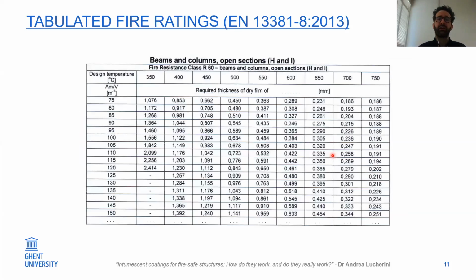So as I mentioned, there are some different engineering methods, implicit engineering methods, to design intumescent coatings, and the first one is the tabulated fire ratings according to the standard EN 13381 part 8. You can see, for example, that intumescent coating manufacturers, out of some fire resistance tests, usually produce tables like that, where you can specify which element you would like to protect. For example, in this case, beams and columns with open sections. Then you see the fire resistance class. In this case, you want to achieve 60 minutes, 1 hour fire resistance.